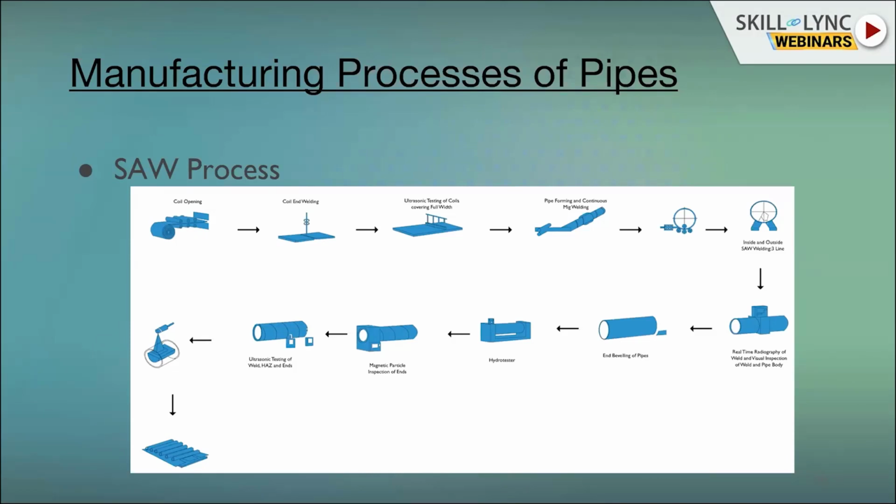Okay. A particular pipe which is required in the line is required to go through the beveling part. Beveling, in the sense, means a pipe end which is cut at a particular angle. In the industry, we use 30 plus or minus 5 degrees. It is cut into that beveling part.